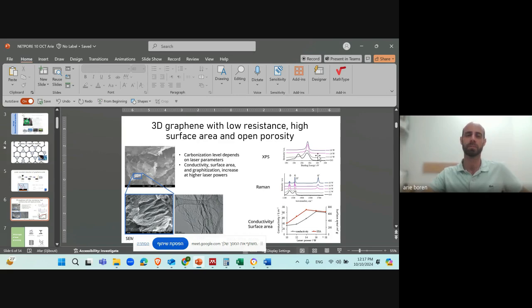As we use stronger laser power, you can see that the peak of the CO is lowered, and we are left with one peak that is getting narrow around the sp2 carbon. And Raman, which is also a very powerful tool for carbon characterization, also shows us very high quality graphene. You see that the D to G ratio and also the 2D band show a very high graphitization level. We can control the graphitization level, the conductivity, and the surface area by changing different parameters in the laser, for example, laser power, the speed of the laser, the environment, and other things. But anyway, we end up with graphene.